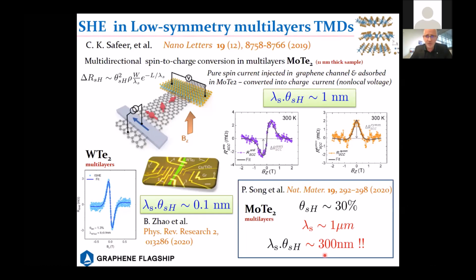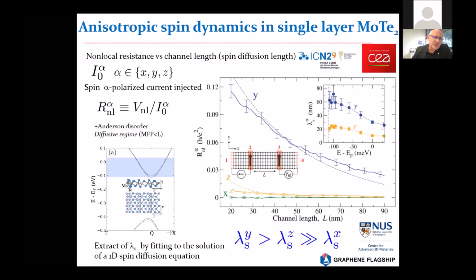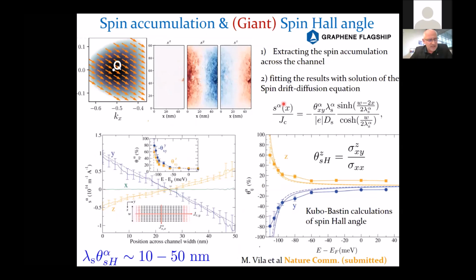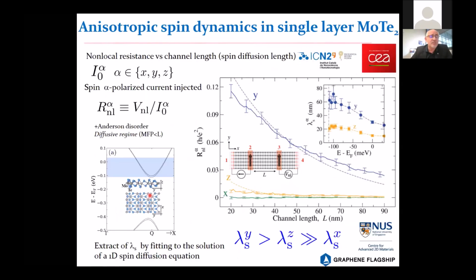So we did the simulation in order to analyze those results, again with our non-local simulation, with some realistic modeling of the molybdenum ditelluride. What we found is that because of some symmetry breaking in this material, there are multiple components of the spin Hall effect, and also the spin lifetime will depend on the injection direction of the spin. It turns out that the spin has a kind of constant spin texture in the YZ plane, which is quite invariant in the Brillouin zone, and this provides a very robust spin signal, as I will show. So here, we extract from the length dependence of the non-local resistance the spin diffusion length as a function of the energy, in the range of several tens of nanometers.